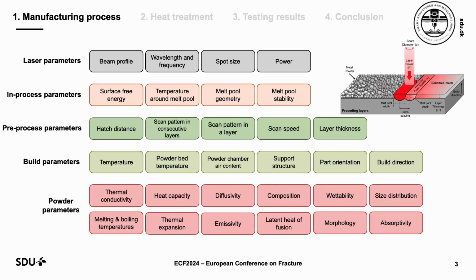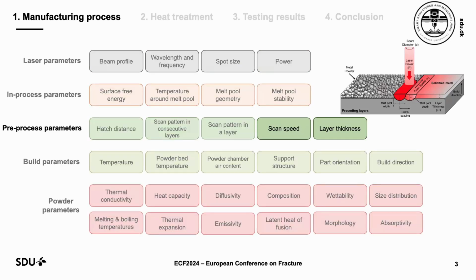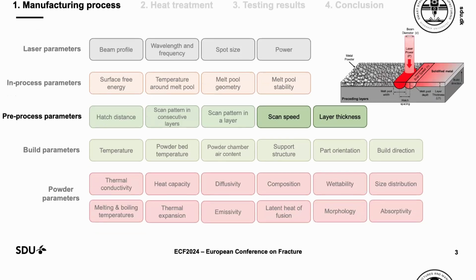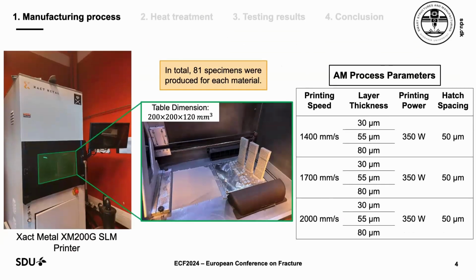In this work, we only focused on scan speed and layer thickness. Other process parameters were kept fixed for different cases, and we only changed scan speed and layer thickness. We used an Xact Metal 3D printer with a table dimension of 200 by 200 and a height of 120 millimeters. And we produced 81 specimens.